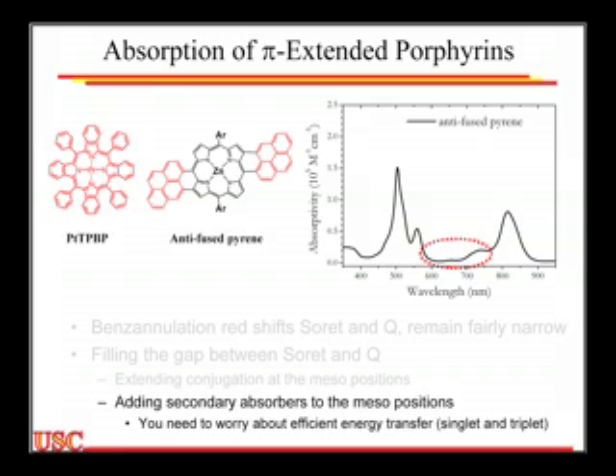So it's a very simple process, a very fast process in single crystals of tetracene for the singlet to split and make two triplets. So if you think about it from a simple arithmetic standpoint, the energy here is 2 times the energy there. So for one singlet, I can make 2 triplets. And so singlet fission is a form of multiple exciton generation that's very promising, and people are pursuing it now. And the picture then changes a bit. So instead of my doing energy transfer from diphenyl tetracene to the porphyrin, maybe I do singlet fission and I do energy transfer from the porphyrin to the triplet of DPT. That's actually a much more important process than the first one.